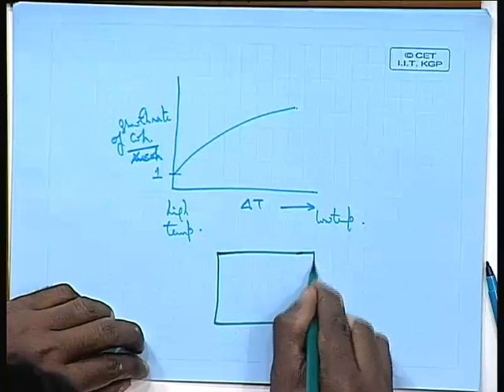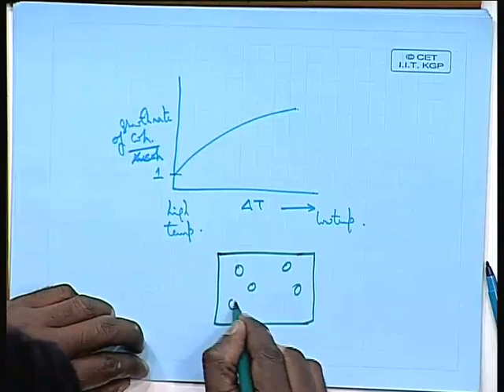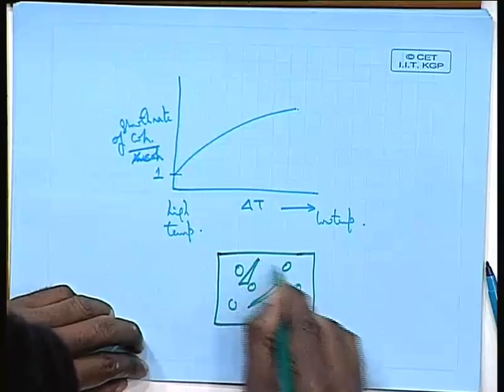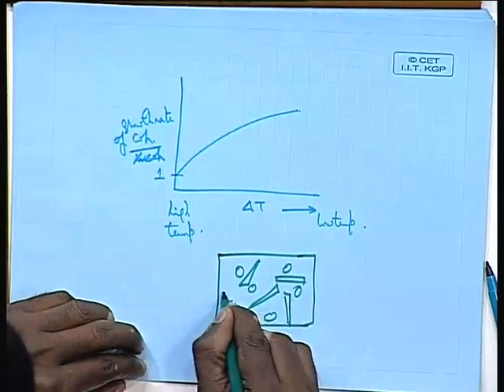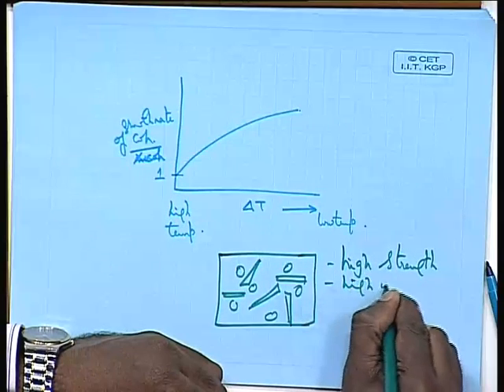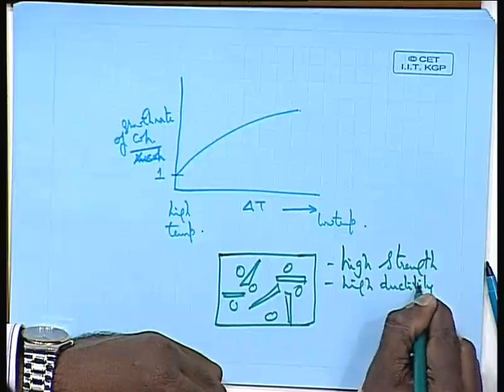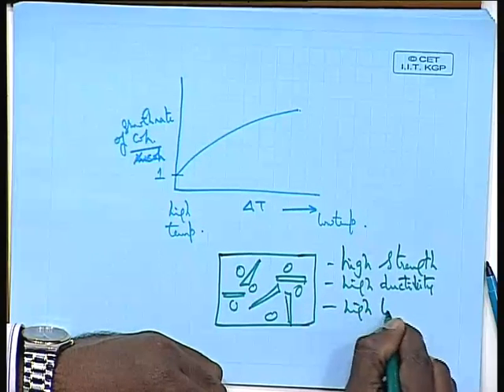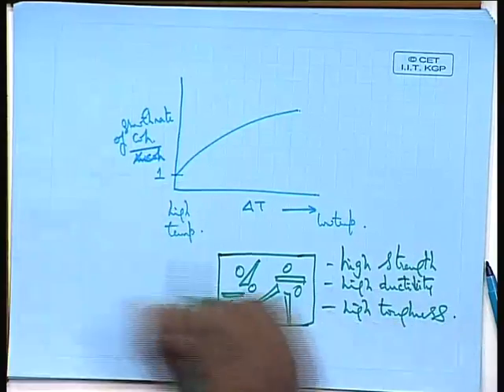So, this is a two-stage precipitation process or two-stage annealing process people have adopted in the titanium based alloys to give you a combination of both, that you have some precipitates which are of this type and some precipitates which are of this type. If you have a combination of these two types, then you achieve what you really are looking for: the high strength, the high ductility, and high toughness. A good combination, I would say. I would not say all of them are very high, but an optimum combination of all the three.